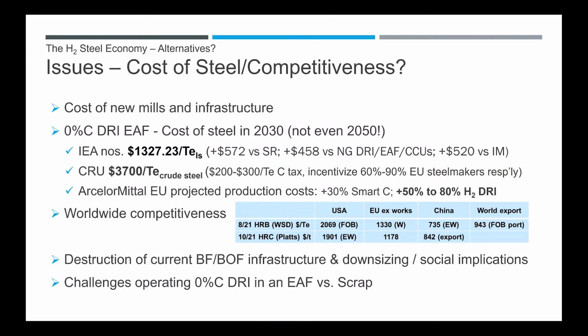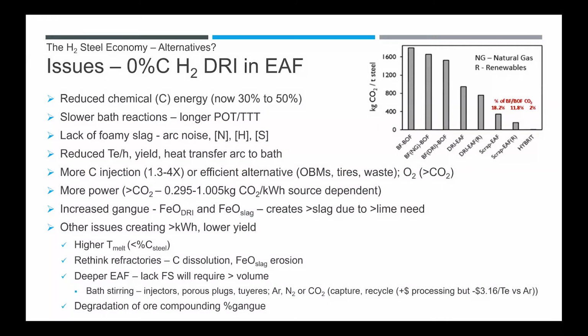ArcelorMittal has stated that their cost of production is going to go up 50 to 80% if they use hydrogen DRI. And the other issue is going to be the worldwide competitiveness against people that are not going to comply. And we've already got a problem, as you can see from this chart, of the USA being more expensive even than the Europeans, never mind the Chinese. Destruction of the current BOF blast furnace infrastructure and downsizing of manpower is going to cause social implications. And of course, there are some major challenges for zero carbon DRI in the arc furnace. Next, please.